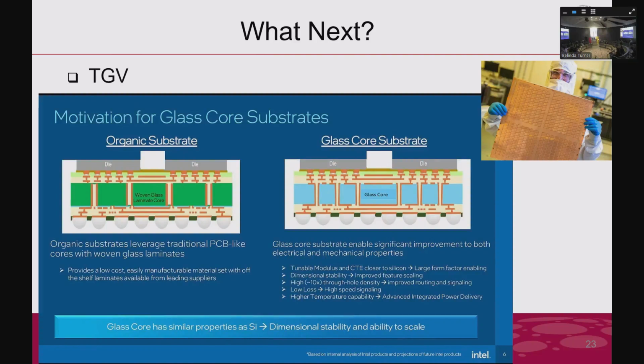The silicon defect is because once you heat up the silicon, because you stack up a lot of chips on top of the interposer, when they are fully running, it generates heat. And the heat will cause signal loss. It turns out Intel changed the idea. They try to use glass to replace it. So that's why I say, in one of my slides, glass can be etched with RIE as well. But the difference is, instead of chemical and physical, like on silicon etching, glass is more about physical etching.